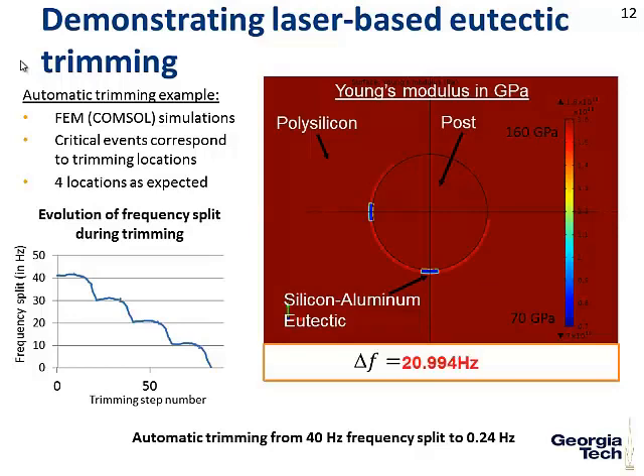So what's really important is that you can see them here, right? The frequency split increases. So you have to stay as small as possible on those bad locations. You find them, you don't touch them. You move on until you find your good locations. And since we know that they are at 45 degrees apart, what you can do is start going around the post until you find one location, and then when you find one, you know the others are at 90 degrees or at 45, so you don't have to actually go on them.